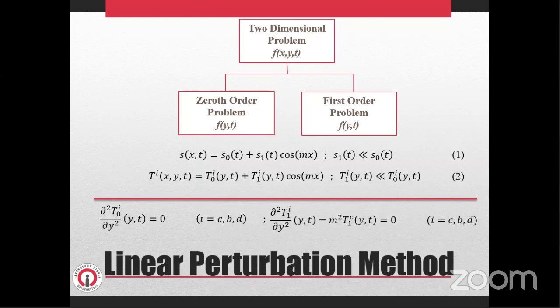If the mold is at uniform temperature, there is clearly a one-dimensional solution to the problem in which the solidification front at any given time is defined by a straight line, y equal to S0t, and all physical quantities are functions of y and t, but are independent of x. If an x-dependent perturbation is to grow on this unperturbed or zeroth-order process, its development will be influenced by the instantaneous zeroth-order quantities. As long as the perturbation is small compared with the zeroth-order values, the perturbation will be linear and permits us to use Fourier transformation on x. This leads to reducing the dimensionality of the problem. Since the zeroth and first order problems involve fields varying in only one spatial dimension and time, they are considerably easier to implement and more efficient computationally than a full two-dimensional numerical solution of the solidification problem.